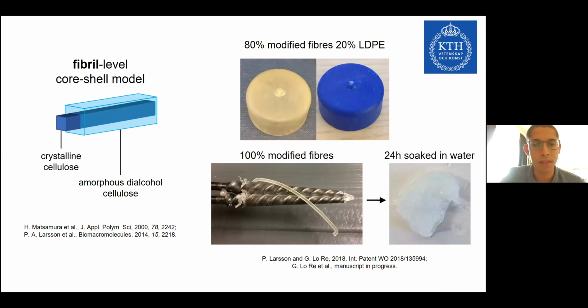Our understanding of the thermoplasticity of this material is based on a fibril-level core-shell model. Because the reactions are done under heterogeneous conditions, what we end up with, we think, is a crystalline cellulose core within the fibril, surrounded by an amorphous dialcohol cellulose shell. On the right-hand side, you can see materials that have been prepared by melt processing. At the top, you have 80% modified fibers and 20% low-density polyethylene, which has been injection molded to prepare bottle caps. Below, you see a proof of concept of the extrusion of 100% modified fiber material. When this material is soaked in water, re-wetted, the wetted material resembles a fibrous soaked material. So we believe we maintain the overall fibrous structures.